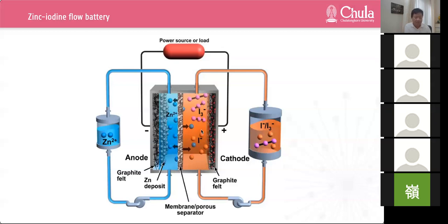So for this system, a high energy density of more than 150 watt-hour per liter is achievable based on the high solubility of zinc iodide electrolyte. The ambipolar and bifunctional design of the zinc iodide battery uses zinc ions as both redox active species and charge carriers, eliminating the need for non-active counter ions. Together with the high selectivity of Nafion membrane against iodine and iodine ions. Wow, Nafion is very effective here to prevent iodine ion crossover because iodine ion is bulky. It's quite large. And the zinc iodine battery system delivers a high Coulombic efficiency, close to 99%. And the cell shows excellent cycling performance.